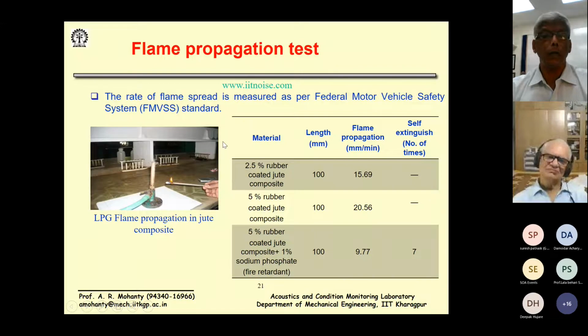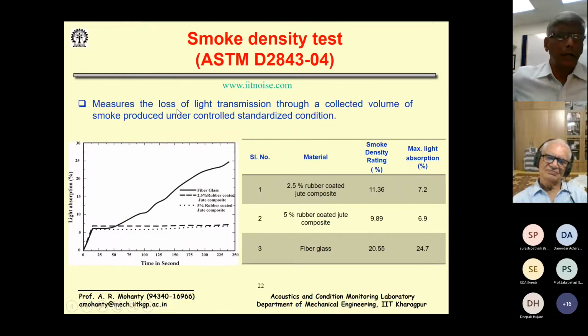Flame propagation, when we tested this sample, compared with the material we manufactured with 1% sodium phosphate applied, it extinguished 7 times. It passed the FMVSS standard and also the UL test standard. So having done all this material testing, we were confident that the jute-based composites which we developed can replace the fiberglass. In fact, the maximum light absorption is also very good, very less being good.